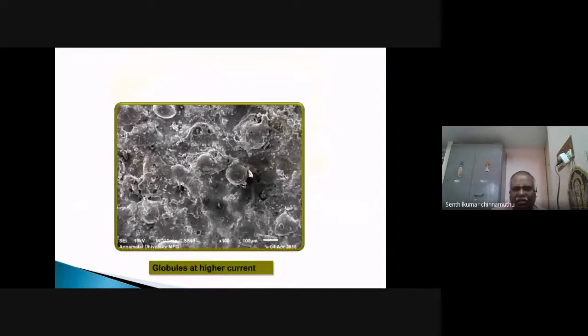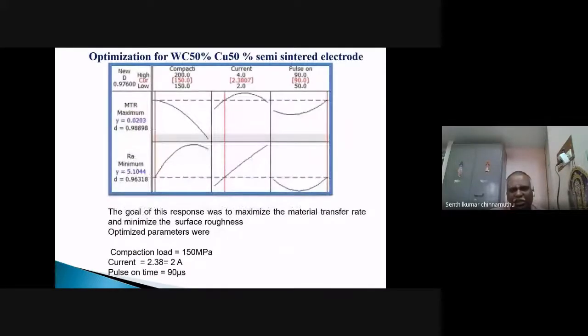That is, the globules are formed due to high current, and more material is melted and again redeposited on the recast layer, which is in the form of globules. So optimization has been carried out to find the maximum metal transfer rate and minimum surface roughness using the RSM optimization technique. Equal weightage is given: 50% for metal transfer rate and 50% for surface roughness.